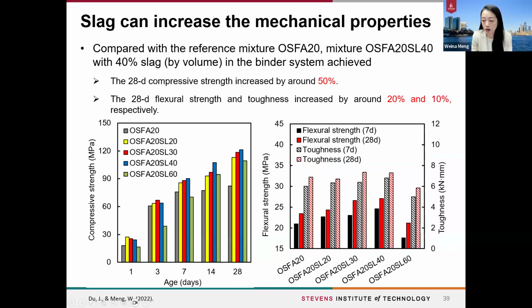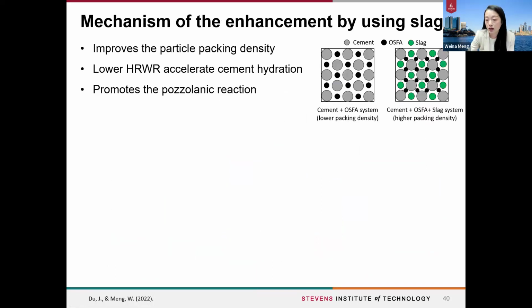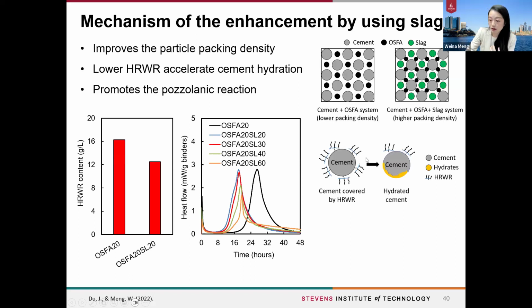But the good thing is that if we incorporate the slag into the system, especially if we incorporate 40% of slag in the binder system, we can increase the 28-day compressive strength by 50% and increase the 28-day flexural strength and toughness by 20 and 10% respectively. The enhancing mechanism is, first of all, that the slag has a different size than the OSFA and the cement, so it can enhance the particle packing density of the microstructure of the system, which can refine the microstructure. And also, due to the improved particle packing density, we can release more free water and reduce the use of high range water reducer.